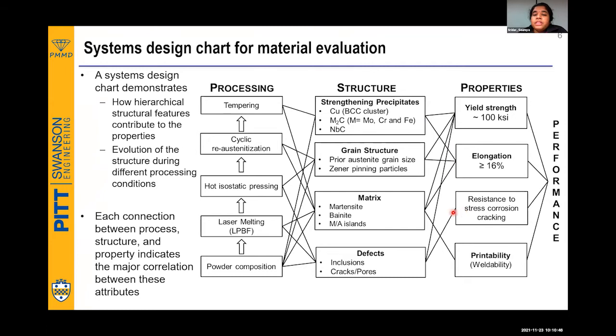Similarly, this is the systems design chart for HSLA 100 steel. So if you consider the matrix, which has martensite, bainite, and austenite. For those who are not familiar with the phases present, martensite is a hard phase, bainite is a soft phase. That will be easy to understand. So the matrix structure is going to influence the yield strength, the elongation, and the printability. Printability here corresponds to whether there is cracking or porosity or not. So again, the defects are going to affect the stress corrosion cracking resistance and the yield strength.